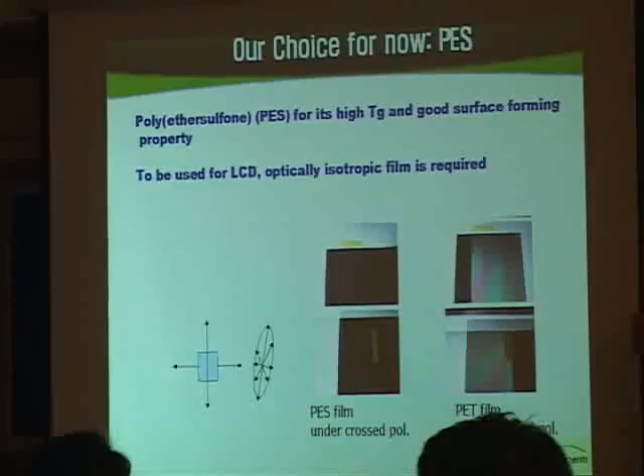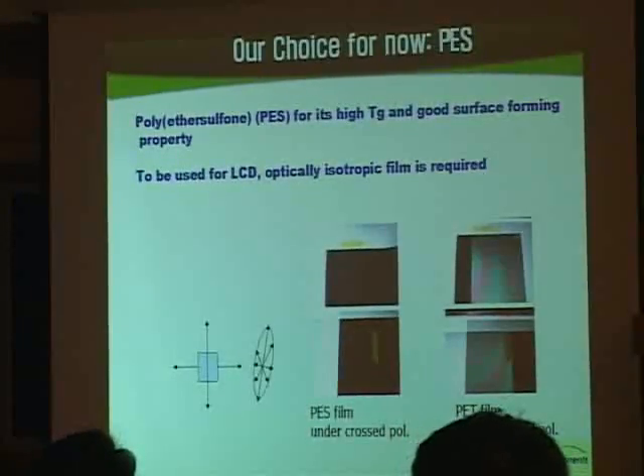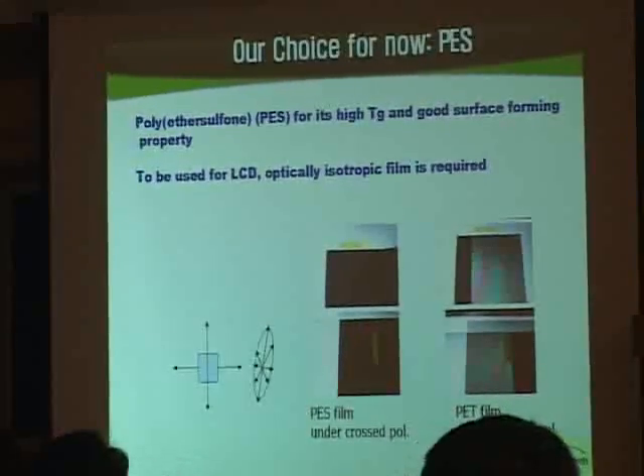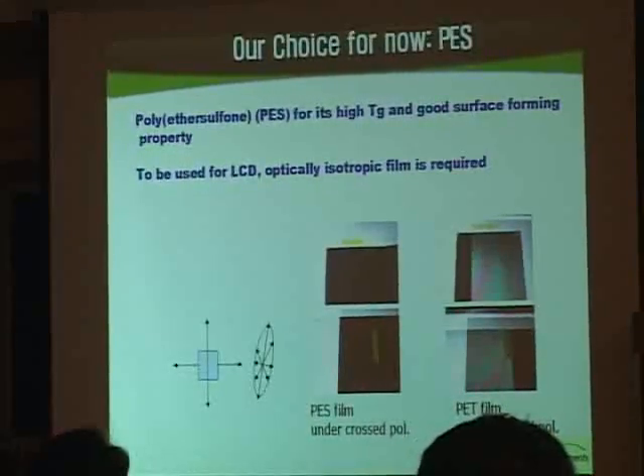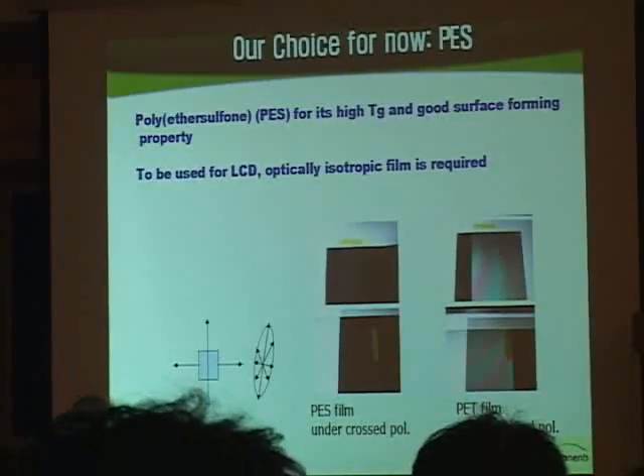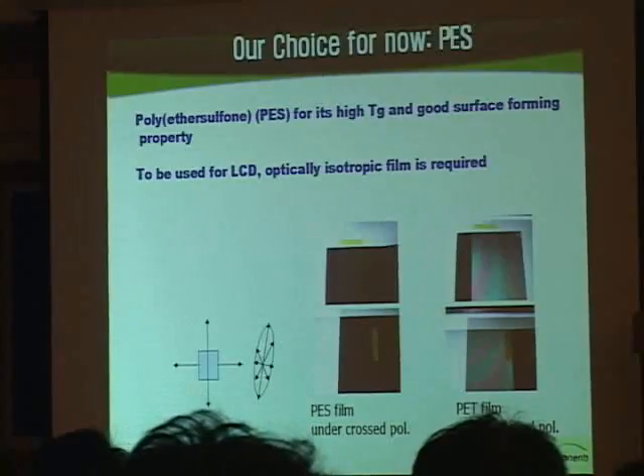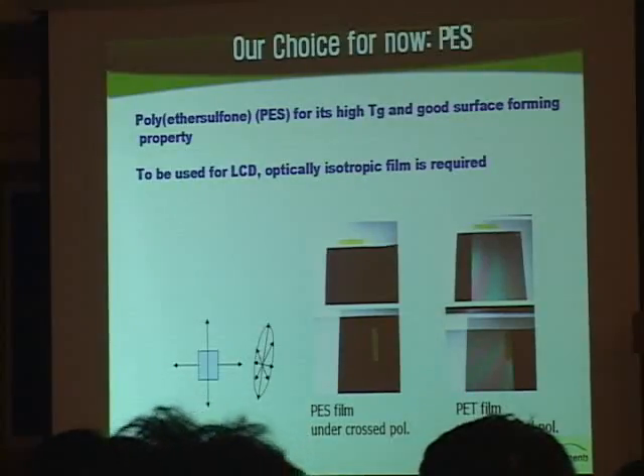Our choice was a polyethersulfone material due to its high glass transition temperature. The glass transition temperature for this material is 225, 230 degrees Celsius. And this is an amorphous polymer. So when you process this polymer, we expect to have a very good smooth surface compared to other types of semi-crystalline polymers. To be used in the LCD, obviously an optically isotropic film is required. And as you see in LCDs these days, it's all based on glass. Glass is optically isotropic.